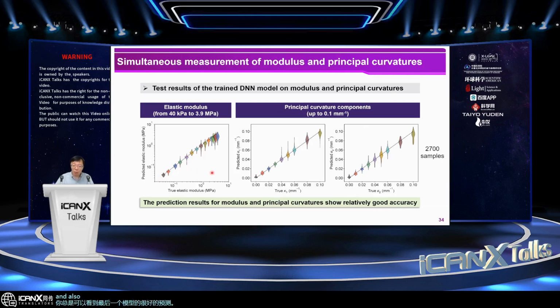And also, we can use this tactile system to achieve very accurate prediction of the curvature, which is the local shape of the object. So when the curvature is below 0.1 per millimeter, we can find quite good agreements of our prediction with the real database.